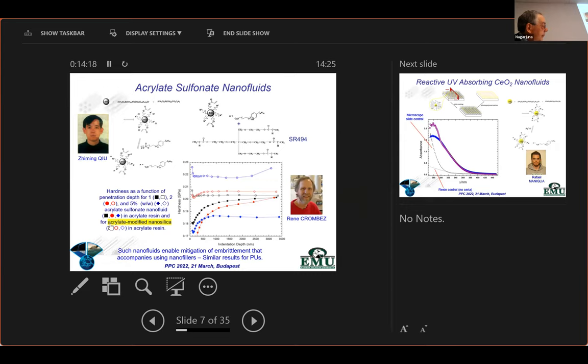And we're looking at hardness here as a function of the amount of this species incorporated at, I think, 1, 2, and 5%. And on the top, we made similar control dispersions without the ionic liquid, just by surface functionalizing the silica with the acrylate group. And you can see the relative hardness. We get the same plot if I plot the modulus. We see as the material gets softer, the hardness decreases. Or in the case of the controls, as we add more, the material gets harder and hardness increases.